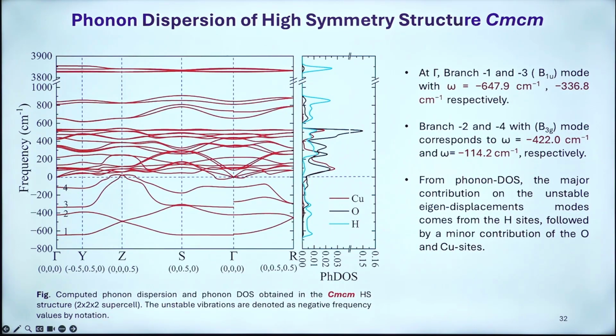The next one: we started with the high symmetry Cmcm structure and computed the phonon dispersion relation, and we could see that there are 4 branches which are imaginary along the entire K path. So you see gamma, Y, Z, S, gamma, R. The phonon dispersion shows that there are 4 branches which are imaginary going along the Brillouin zone. At the gamma point, branches 1 and 3 correspond to the infrared B1u mode, having frequencies of -647.9 and -336.8 cm^-1, and branches 2 and 4 correspond to Raman active modes.